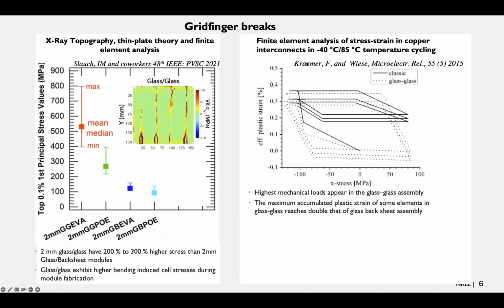Then also, finite element analysis of stress and strain in copper interconnects in temperature cycling. They found the highest mechanical loads appear in the glass assembly, and that would be the dotted lines here. More importantly, this area in the glass modules, in the space of stress and strain, was the greatest. The maximum accumulated plastic strain of some elements in the glass reaches double that of the glass backsheet assembly. So there's quite a bit of stress formed apparently in glass modules that manifests at the edges of the ribbons, and that could be contributing to the failure.